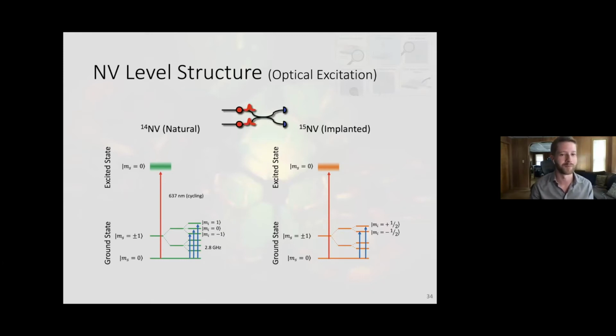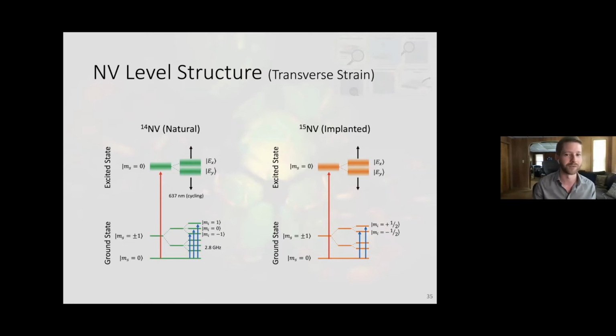So that's the most important fact that we're going to be looking at here. And it's important to note that this actually splits out into an EX and EY transition, which given transverse strain will split out further, and given axial strain will just shift the energy of that excited state transition.